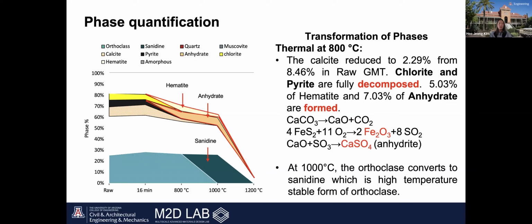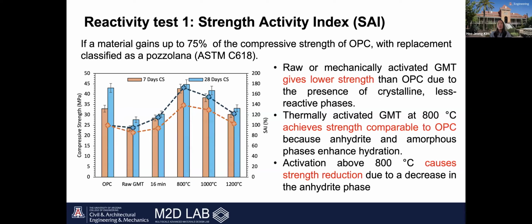And as the temperature increased further, the amorphous content rose from 19% in the raw material to almost 95% at 1200 Celsius degree. And this shows that higher temperature breaks down crystalline phases and creates highly reactive amorphous material. The easiest way to evaluate reactivity is by looking at the compressive strength with the strength activity index.